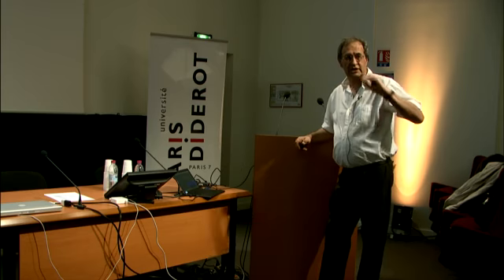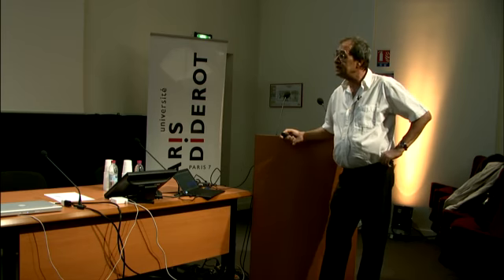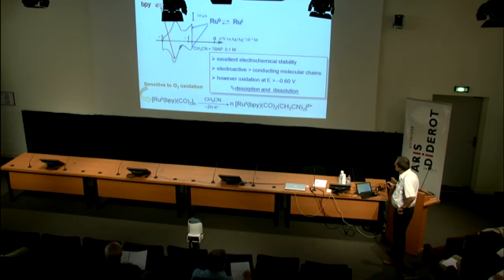It corresponds to the injection of the electron into the ligands, and here that corresponds to the oxidation of the metal. This kind of film exhibits excellent electrochemical stability. If the oxidation is stopped at minus 0.6 volt, at that stage there is desorption and dissolution of the film, and as I said, films are electroactive.